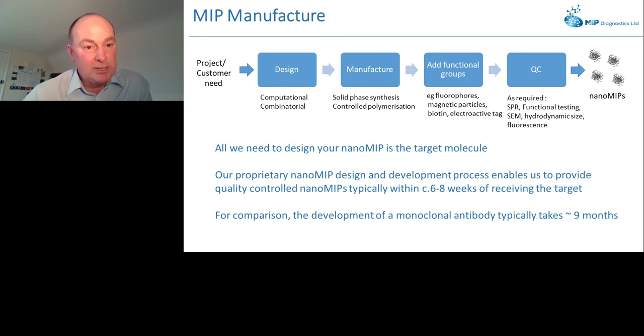So if you had, for example, a cofactor binding to a protein, an enzyme, we can mimic that with a monomer and bind to the same site. If you had a drug that bound to a known site, we could target that by using similar chemistries to make monomers that are similar to those and build MIPs around that site. Computational chemistry can be used, and indeed we hold a patent on the selection of monomers in silico for further development into MIPs.